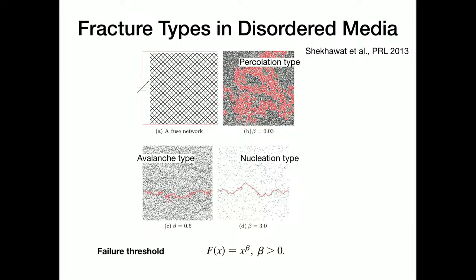So what is seen is that for low beta, that's one of the extremes. Low beta means you have a very highly disordered material. What you see in red is the spanning cluster, the largest cluster that is spanning the width. You could call it, for instance, a fracture path. And for high disorder, you see that it is very ill-defined and all over the place, and what you call the percolation type of fracture. The black dots are the other damage events which are not part of this cluster, and you have a high density of them.